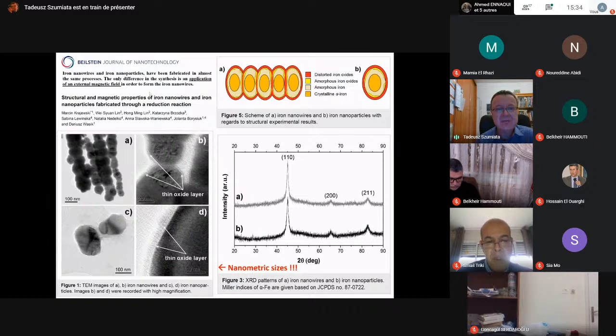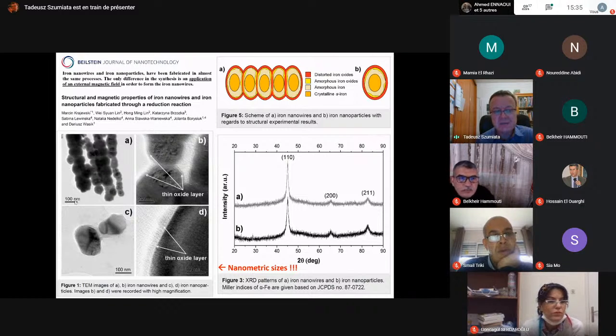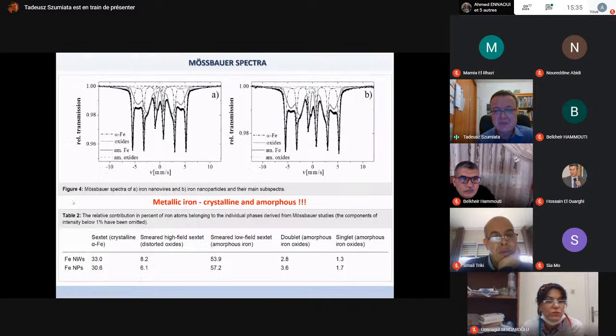I was looking through our old papers made not by me but our team in our Mössbauer laboratory in cooperation with some other groups in Korea, for example, and in Warsaw. And here you can see intentionally prepared iron nanowires and iron nanoparticles of the size less than 100 nanometers. And in the Mössbauer spectra, you can see, okay, metallic crystalline iron, but also we call it amorphous iron, very